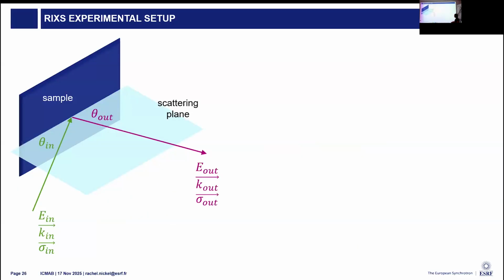So our experimental setup, I've shown this with a horizontal scattering plane initially. So we can choose the energy of the beam, the momentum that we're choosing, that we orient the sample to relative to the incoming beam, and the polarization. So the polarization here is sigma. And then we measure in the outgoing plane the energy out. This, we measure the entire spectrum.